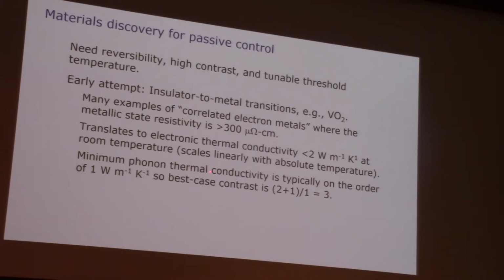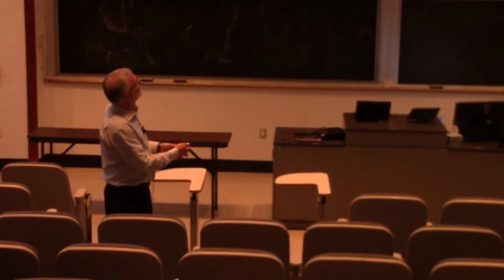I already talked a lot about minimum thermal conductivity of phonons. In these kinds of materials, that's typically on the order of 1. So really, even if I made this material as good as I could make it, I probably can't get a contrast better than 3. In other words, I have 1 watt per meter Kelvin, the thermal conductivity increases by 2 to 3 watts per meter Kelvin at higher temperatures, due to the electrons turning on. Right? Well, it turns out we were never able to see anything that big. We worked actually really hard on this with a group at Toyota Research Institute of North America, and the best we could ever get was still less than 2. But that was kind of the best we could do.